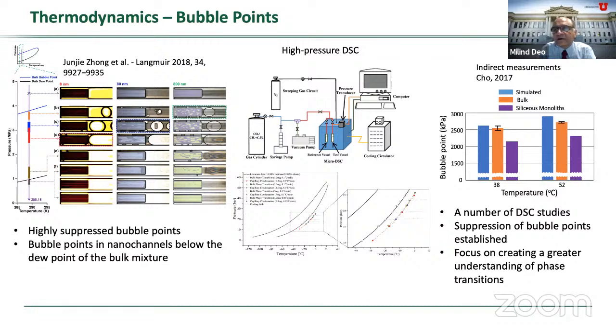Again, the question that we asked ourselves was rather simple. I showed you that Bakken plot where the gas oil ratios appear to take much longer to go into what we call free gas flow compared to conventionals. So in conventional, usually if the bubble point pressure is not very much below the initial reservoir pressure, then within a few weeks or maybe a couple of months, you can expect free gas flow to start. And then the gas oil ratios increase.